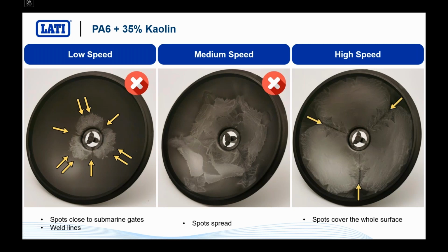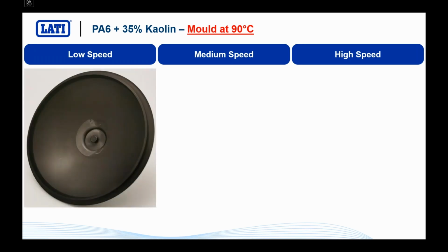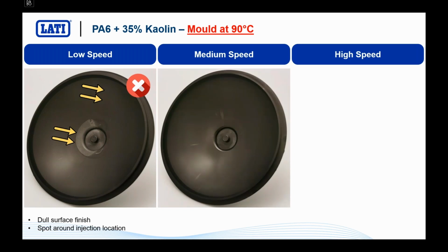Let's see what happens if we work a little bit with our tool temperature. Let's raise the temperature of the tool just by 10 degrees C. Remember, we fixed the temperature of the tool at 90 degrees C. We just moved it from 80 to 90. So it's just 10 degrees C more. And you can really appreciate how the situation will somehow be solved by helping the material to properly flow and to properly disperse the filler.